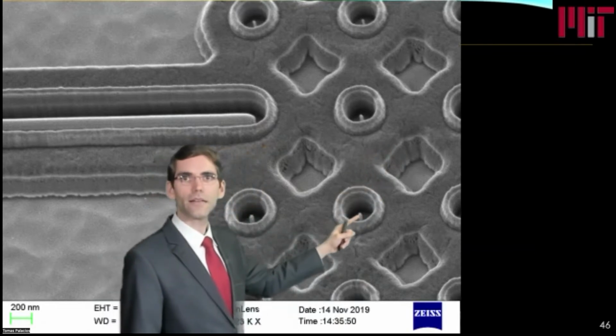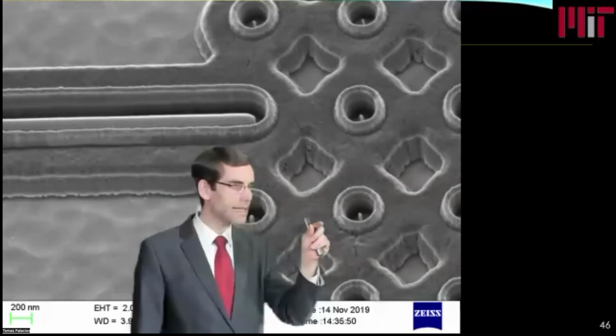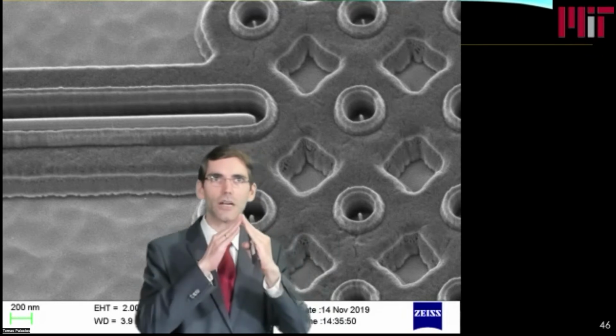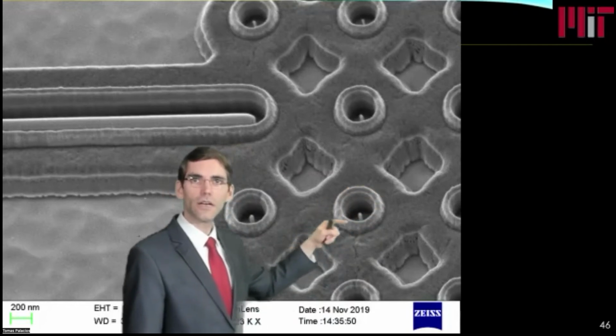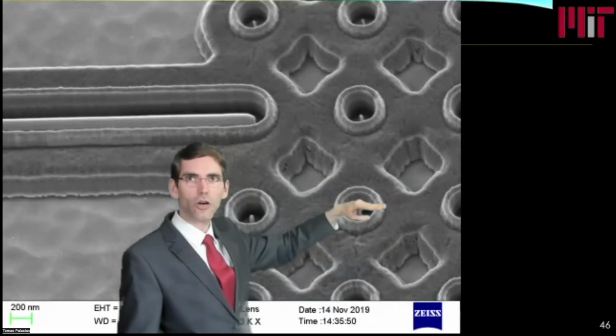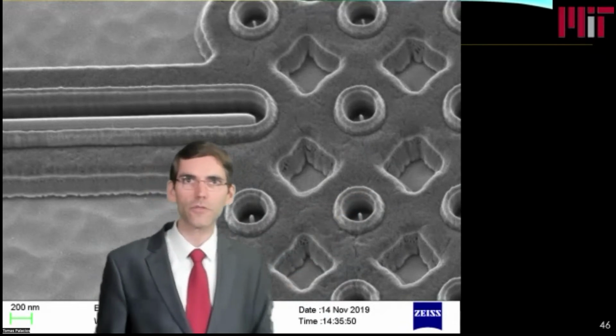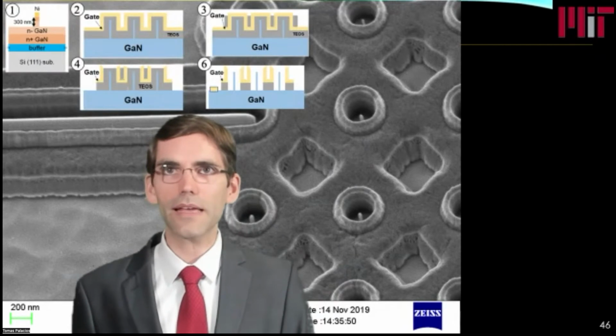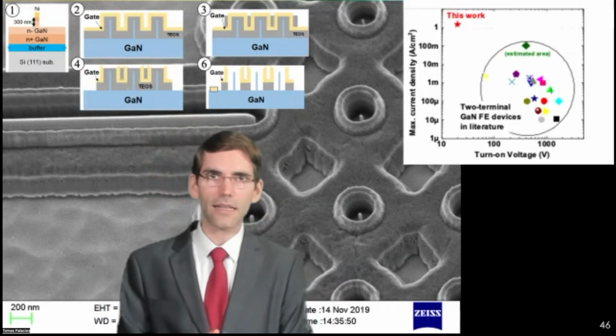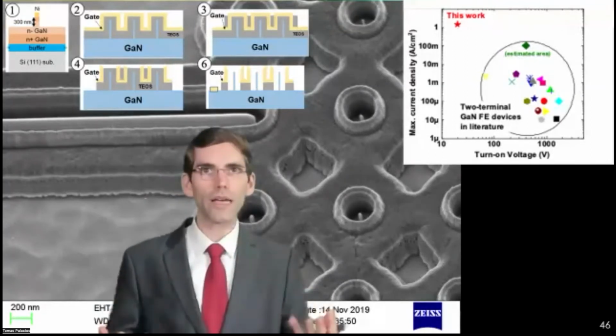And we started to build these devices. This is an SEM image of the gallium nitride tips right there. They are typically 20 to 50 nanometers in diameter, and right at the tip, the radius is around 10 nanometers. You need very sharp tips to make sure you can extract the electrons very easily. These round structures are basically the gate electrode. And then what we don't show is the top electrode, which in this case has been removed. So this is how we fabricate it, and the bottom line is that what we have today looks quite promising.